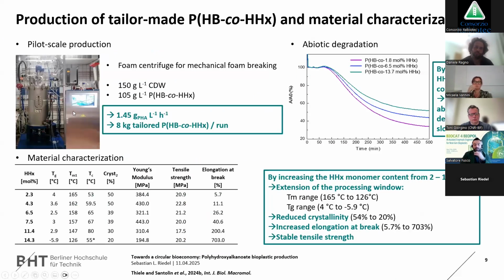So then we also did some material characterization with partners, of course. So you see what I said, how the different characteristics, from temperature to elongation at break, so how long you can stretch it before it breaks, have an impact on the HHX concentration. And also some abiotic degradation with the partner. This goes much faster than biodegradation tests, which can give you an idea about the degradation later on. And there we can see, as I said, PHA is very easily biodegradable. With longer HHX, it gets a little bit slowed down, but it still gets degraded.